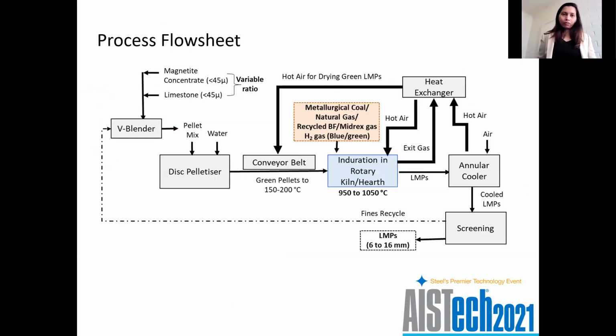With the pilot testing results, we have also proposed a flow sheet of the LMP process. This is similar to the current pelletization process, with blending, like with a blender, to mix the feedstocks together, followed by a pelletizing stage, then a conveyor belt to transport these pellets to the kiln, and also dried